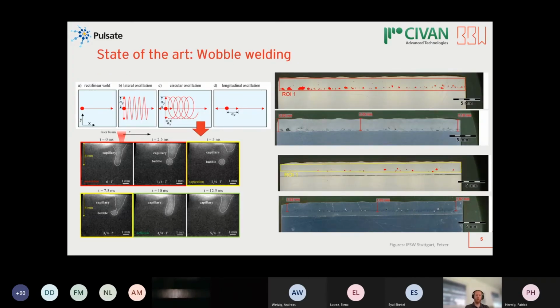So I want to shortly present 2 existing strategies already very well established in the industry. One strategy against welding defects is wobble welding. We have 2 mirrors inside the scanner. The combined movement results in a 2-dimensional, very dynamic movement. So for example, by using a circular oscillation geometry, the laser beam passes over the same position several times and interacts with possible gas bubbles inside of the melt, which leads to degassing.